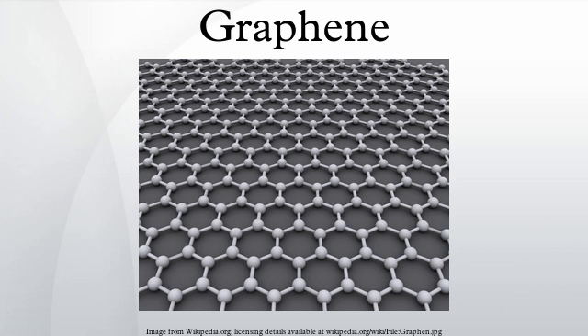Immiscible liquids: sonicating graphite at the interface of two immiscible liquids, most notably heptane and water, produces macro-scale graphene films. The graphene sheets are adsorbed to the high-energy interface between the heptane and the water, where they are kept from restacking. The graphene remains at the interface even when exposed to force in excess of 300,000 G. The solvents may then be evaporated. The sheets are up to 95% transparent and conductive.